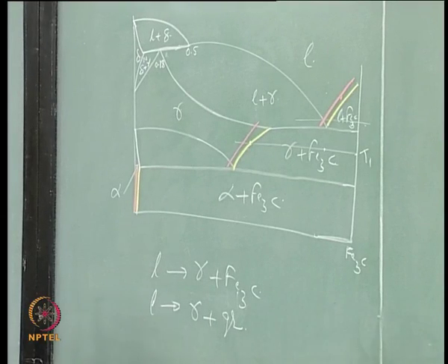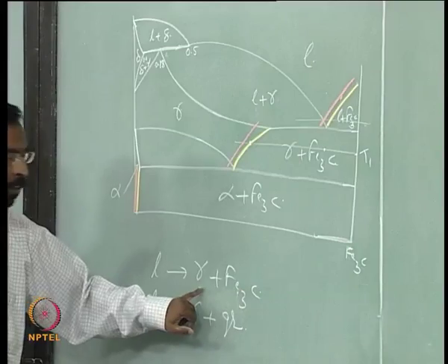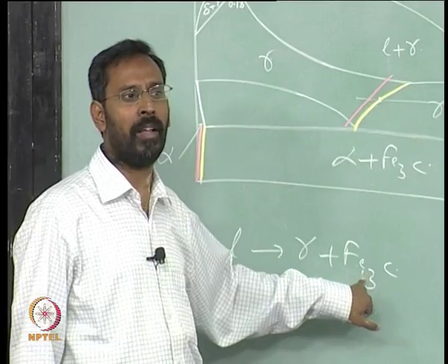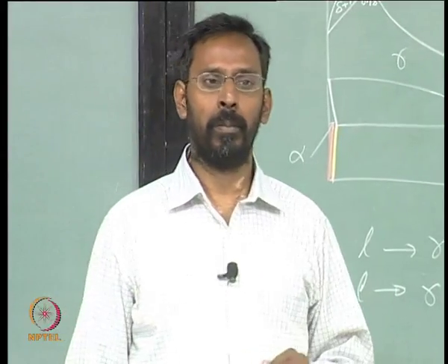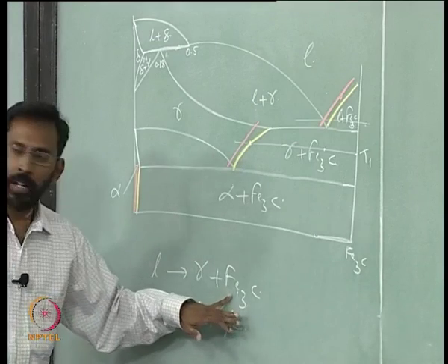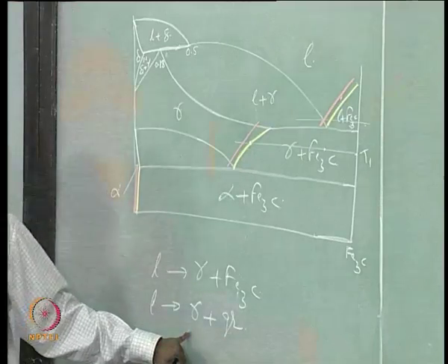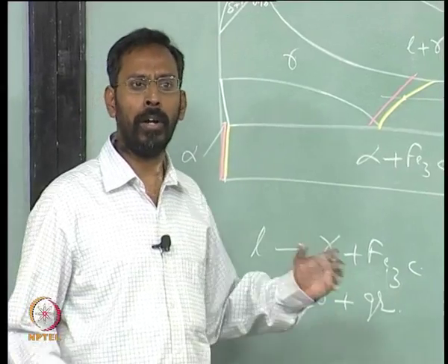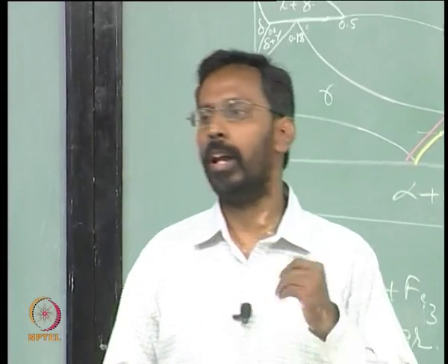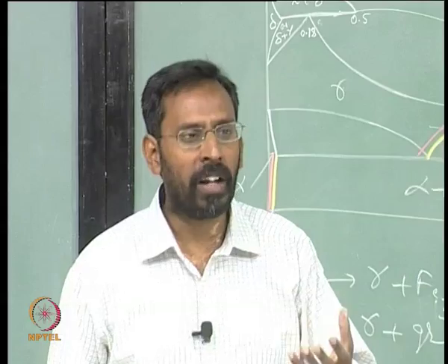Which one? Graphite. Because when I am thinking of the reverse reaction of this, cementite plus gamma giving you liquid, because cementite is a metastable phase, it wants to convert into a stable state at a lower temperature. So, the melting point of the cementite gamma eutectic is lower than the melting point of the graphite gamma eutectic. So, graphite gamma eutectic will have a higher eutectic temperature, cementite gamma eutectic will have a lower eutectic temperature, because it is a metastable eutectic. This is a stable eutectic, this is a metastable eutectic, and that is the reason why you would see